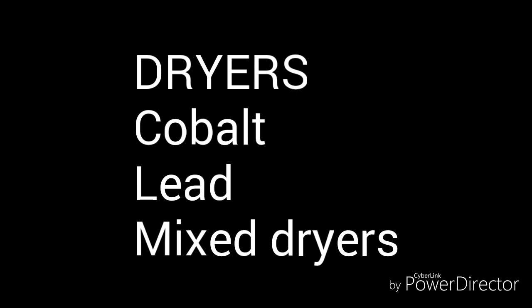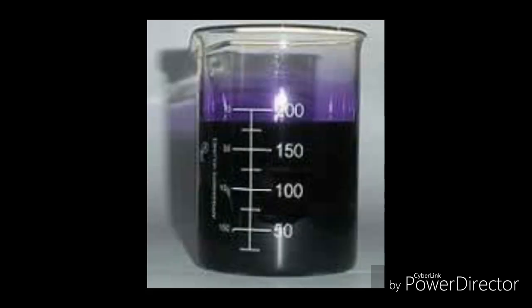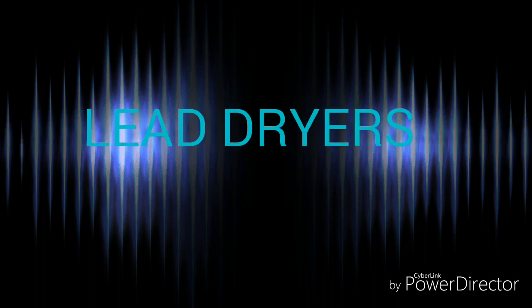In this training, we'll be using lead dryer, cobalt dryer or mixed dryer. Cobalt dryer is the most preferred. It's compatible only with certain darker pigmented paints like black, orange, green, blue, ash, or red, because cobalt dryer is a deep blue purple in color. It can hinder the brightness of lighter pigmented paints. So I'm going to use lead dryer on colors like cream, white, off-white, and other paints.